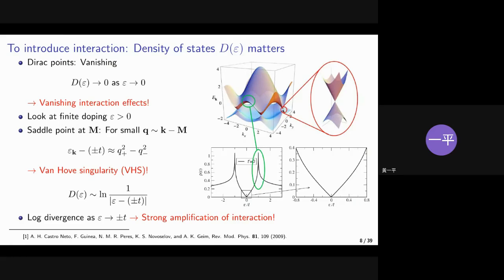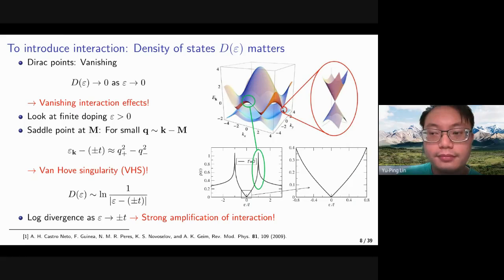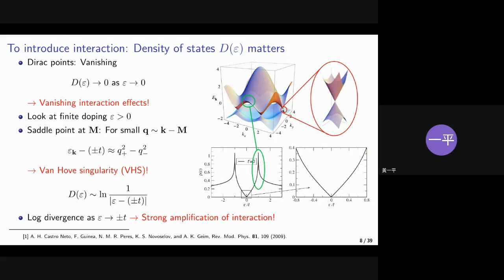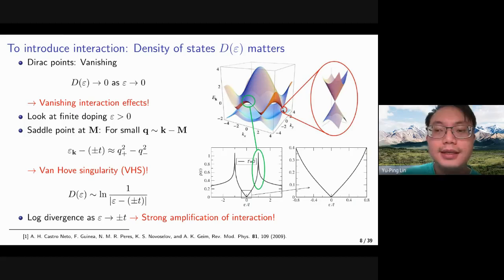Yeah, sure. So the argument is that when the energy goes to zero, that's when you reach the Dirac points, the density of states vanishes. But because the density of states vanishes, doesn't that mean the screening effect will also be suppressed? In that sense, the interaction effect is not so trivial to drop. So yeah, that's true. It is in the weak coupling limit actually. If we have a stronger coupling indeed, there might be some correlated phases that are not screened out. So there are some other kinds of correlated phases. But if we focus on the weak coupling limit, then we can think of it as effectively non-interacting.